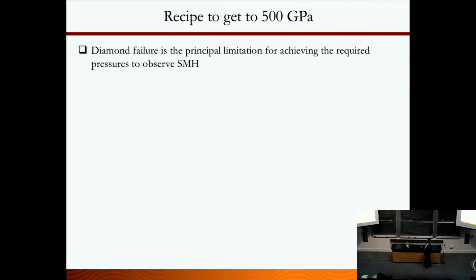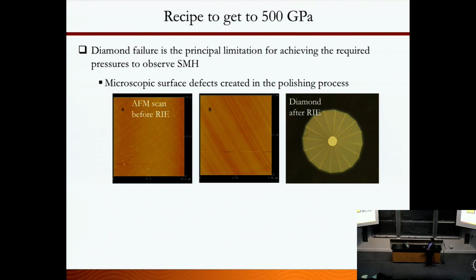One thing we did was address the failures of diamond, one cause of which is microsurface defects. When you have a nicely polished diamond and look at it under the atomic force microscope, you can see defects. So we use the RIE technique to remove those defects and make a nice smooth surface, so that it will not let hydrogen get in and break the diamond. This is what the diamond looks like after RIE. Another thing is that hydrogen is very diffusive. It goes into the diamond and cracks it, and that prevents us from reaching higher pressures.